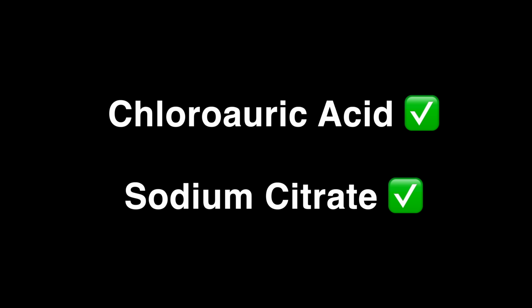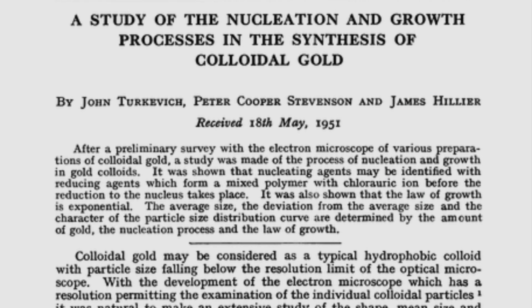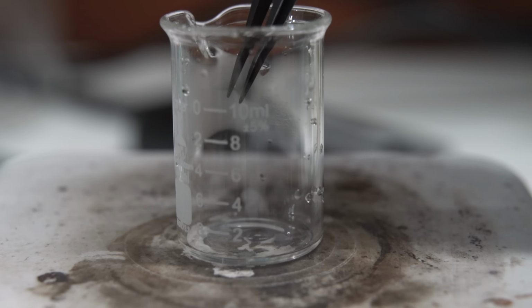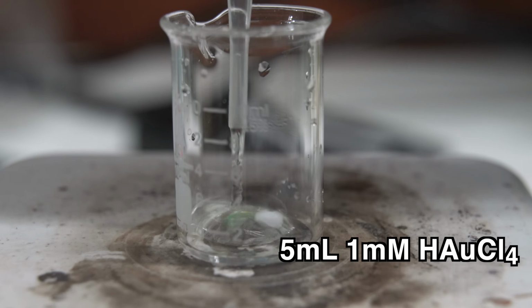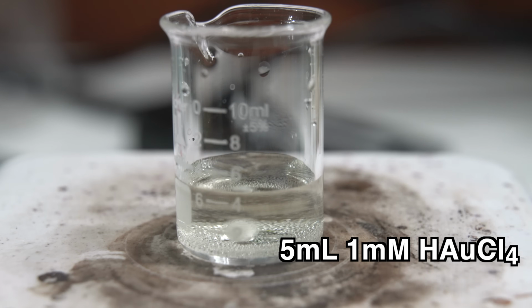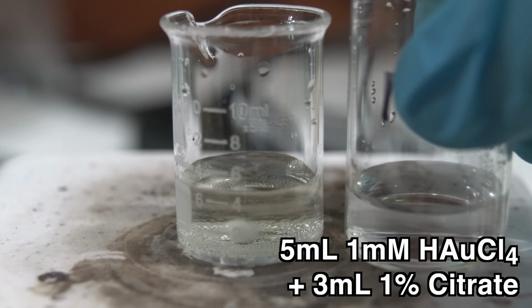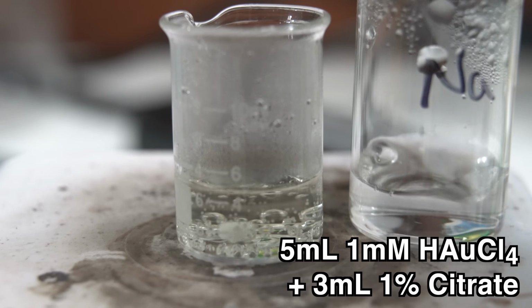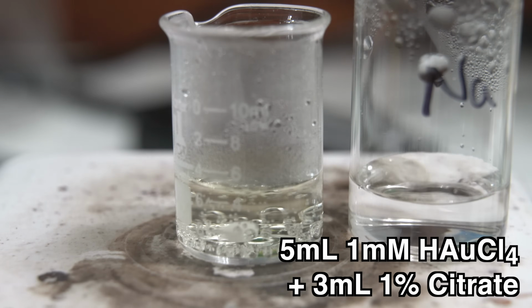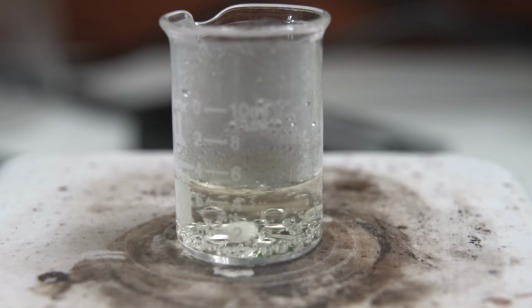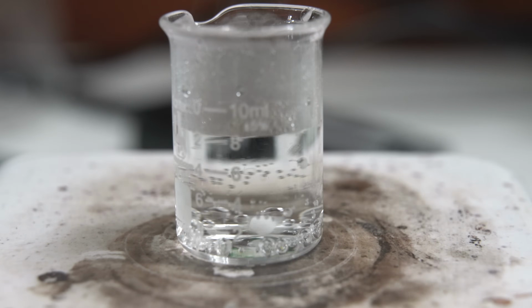Now that we have all the necessary chemicals, let's make some nanoparticles. I'm going to start by following the Turkevich method, named after the scientist who developed an easy and repeatable method for the synthesis of gold nanoparticles. We start by preparing a tiny beaker and a stir bar. We add a very dilute solution of chloroauric acid to the beaker, and we prepare a sodium citrate solution in a second container. Then we bring both solutions to a boil. We then add the boiling citrate to the chloroauric acid, and we wait.